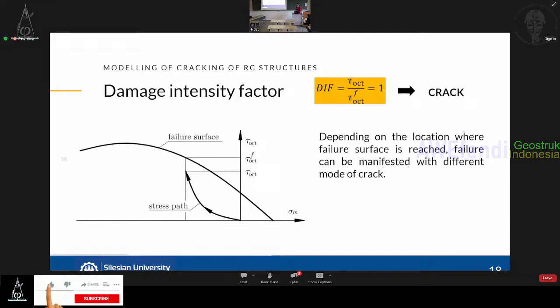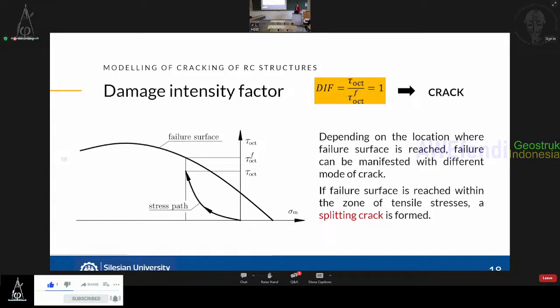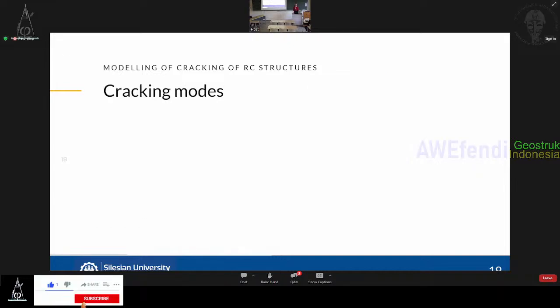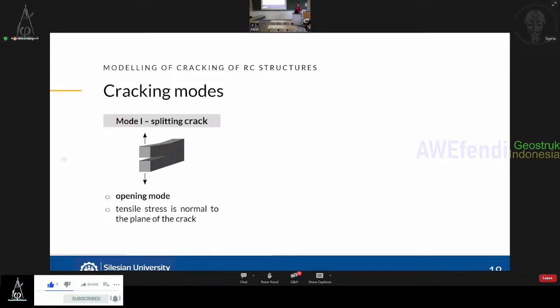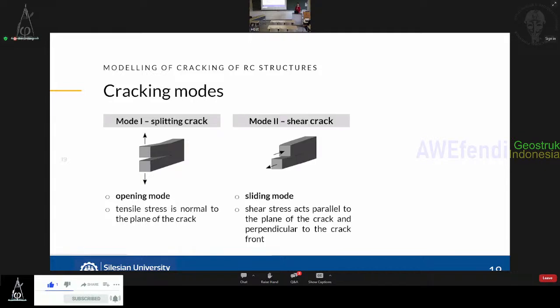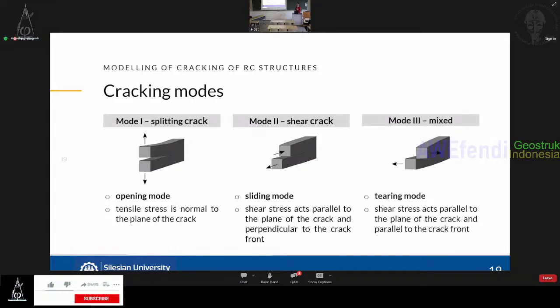And as I said, depending on the location where this point reaches the surface, the failure is manifested with different modes of cracks. The mode which is most interesting for us is the one in which we have a splitting crack, and such a splitting crack is formed when the point representing the stress state reaches a failure surface within the zone of tensile stresses. However, we also have different cracking modes. Apart from the splitting crack, which is the opening mode and appears when the tensile stresses are normal to the plane of the crack, we also have a shear crack. And we can have a mixed crack in a tearing mode when we have a complex stress state. However, as I said, for us in our research and in design, we are most interested in the splitting cracks.